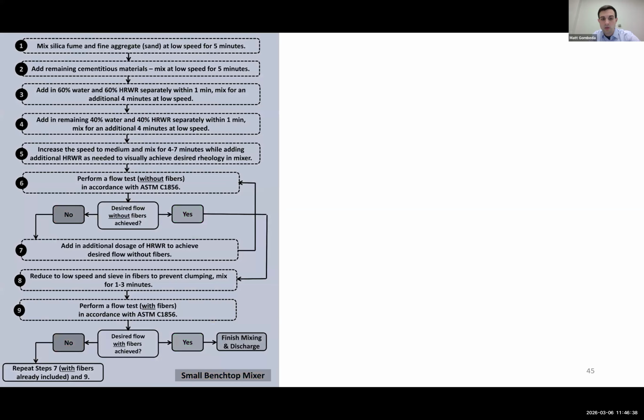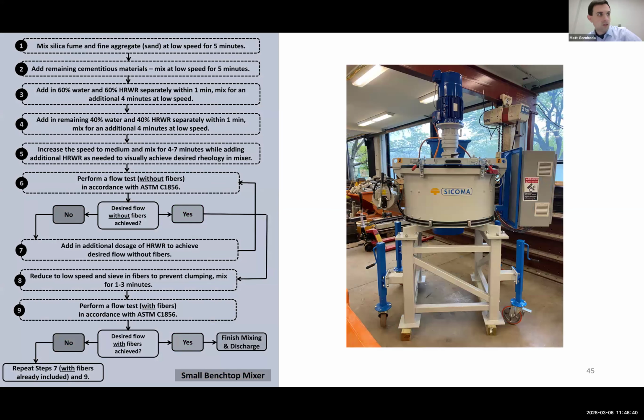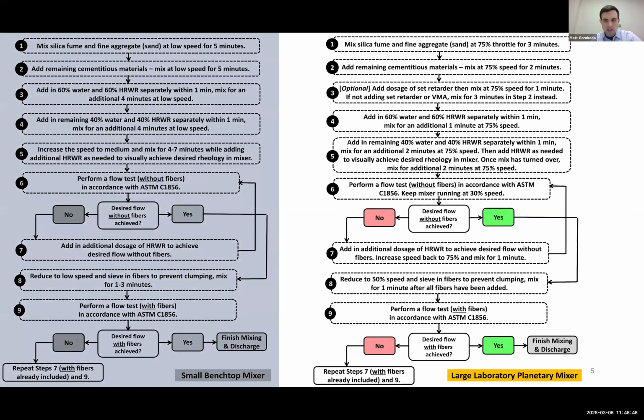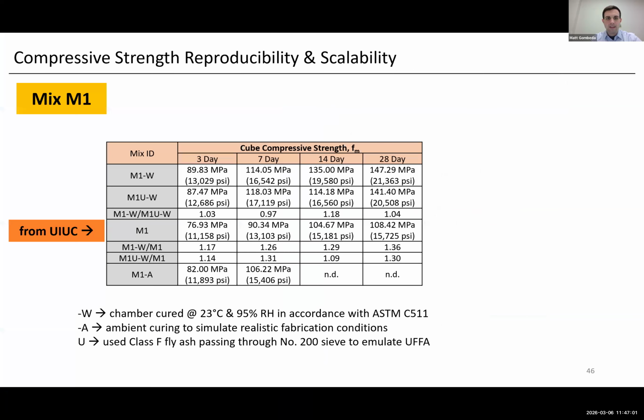But that one was ultimately then superseded at the larger scale when we went up to the bigger mixer. And you can see it's very similar to the framework, but it's a little bit different because we went to dial in how the larger quantity of concrete affects this work and the different type of mixing action and those sorts of things. And so what we did was we got these results for a couple different variations of the UHPC mix.